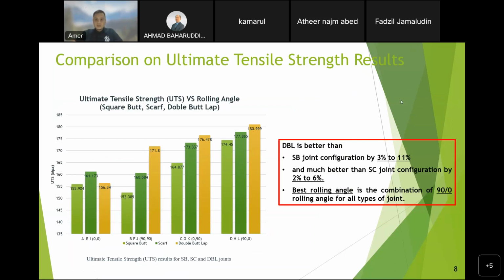We can see that DBL, or double butt lap joint, is better than square butt joint configuration by 3 to 11%, and better than scarf joint configuration by 2 to 6%. And the best rolling angle is the combination of 90 and 0 rolling angle for all types of joints.